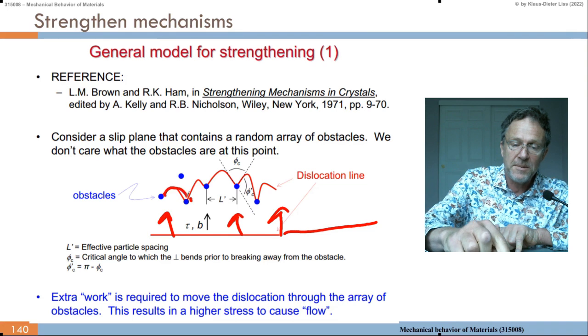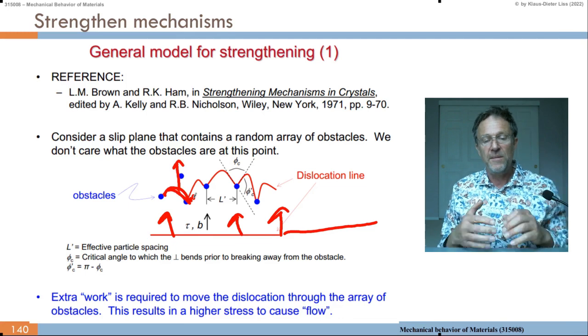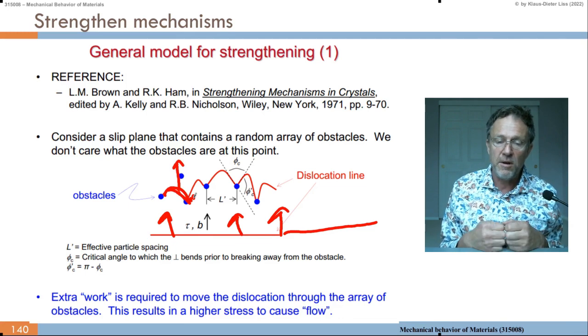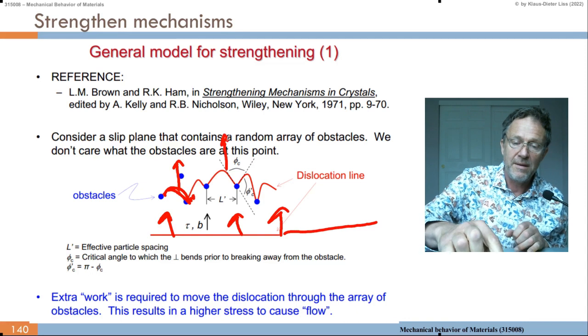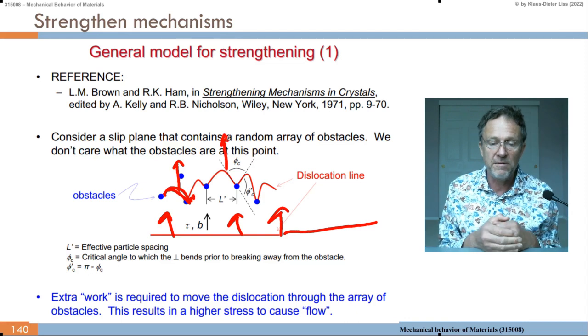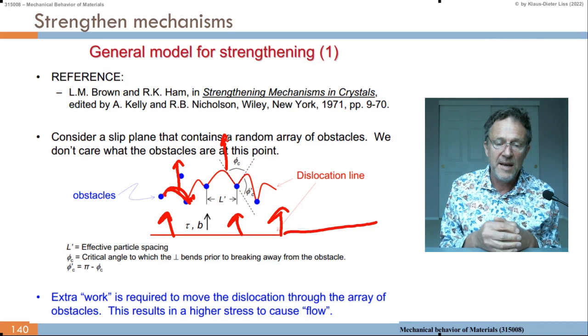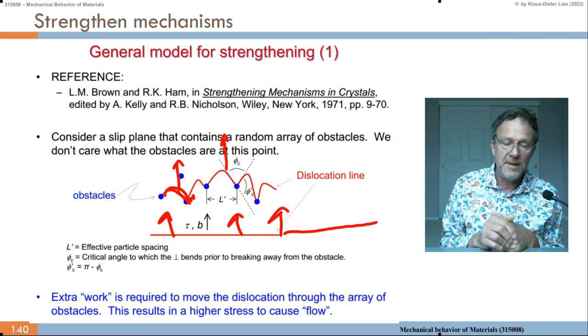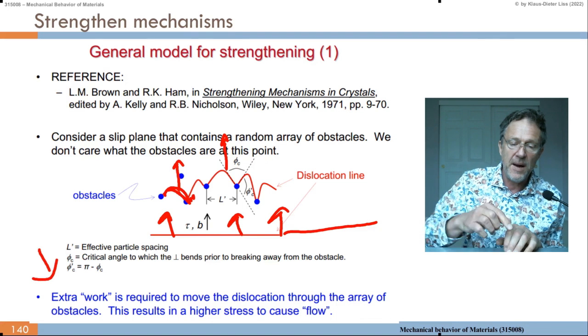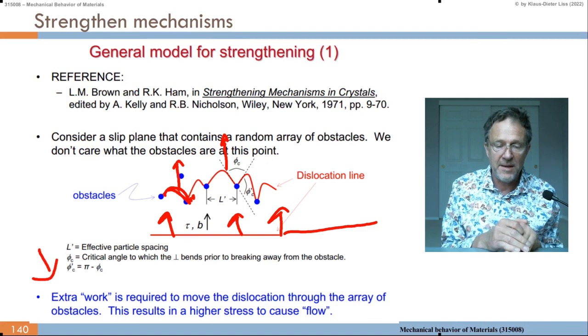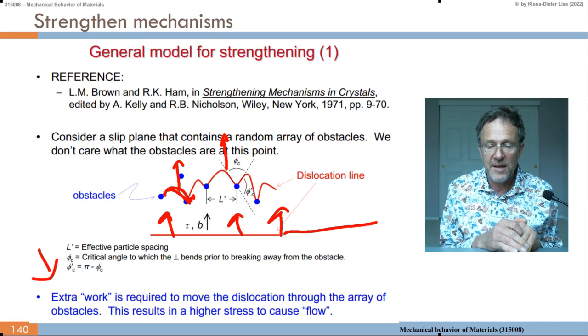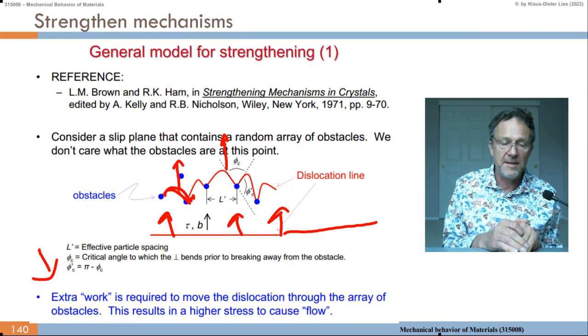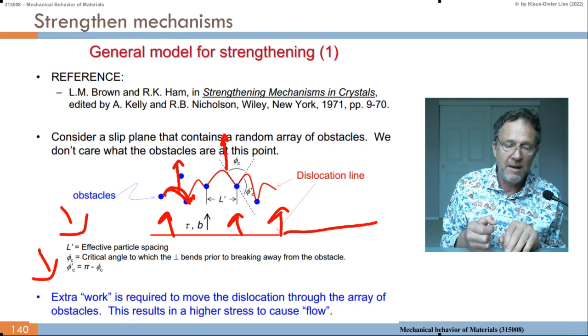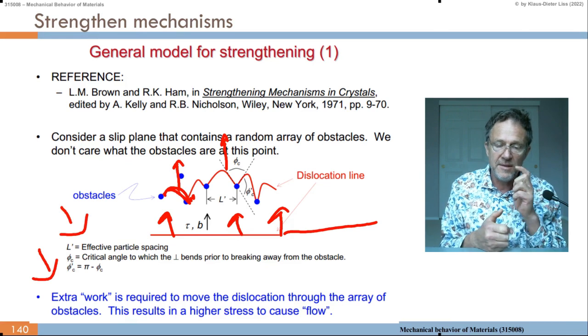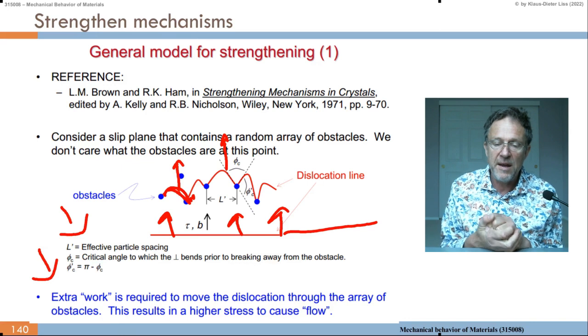So it gets pinned at the obstacles, and between the obstacles it can move forward, but it still remains pinned. So the dislocation line becomes longer because of the curvature. It bulges out. It wants to go in the direction to the top of the graph. It bulges out, it gets curvature, it gets an angle in between. So we need extra work to move the dislocations through the array of the obstacles, and this results in a higher stress to cause the flow. You can do that quantitatively by looking at the effective particle spacing, the critical angle to which the dislocation bends prior to breaking away from the obstacle.